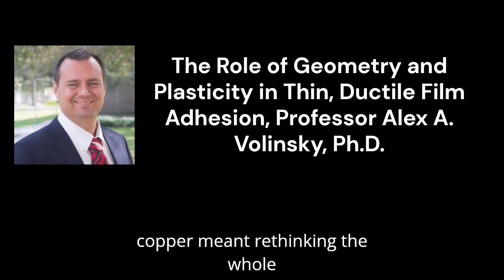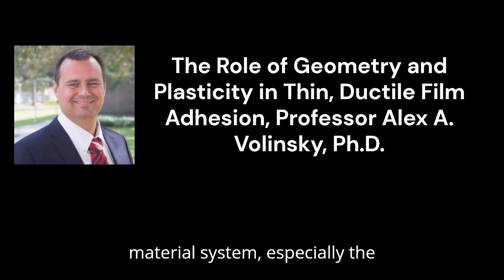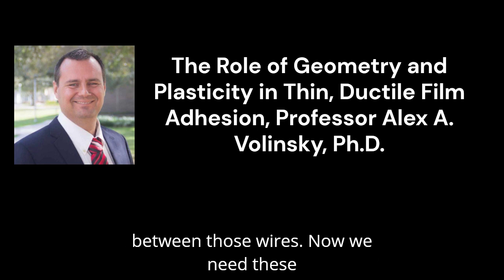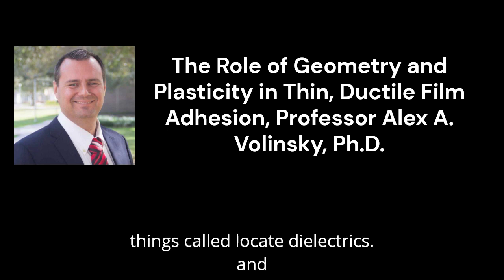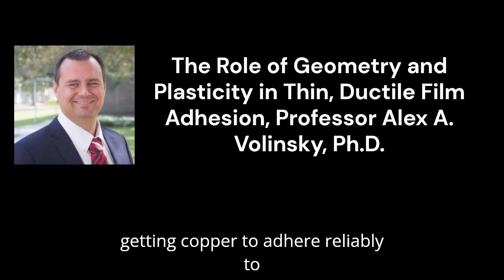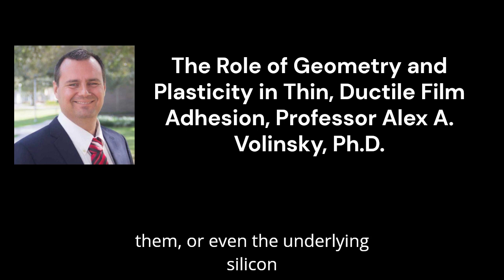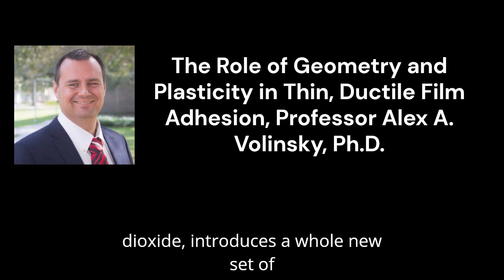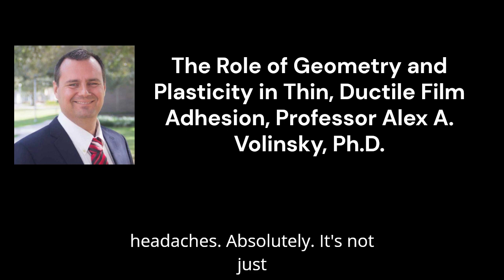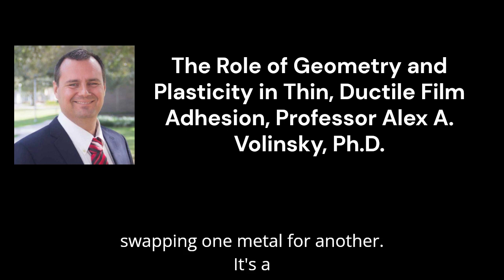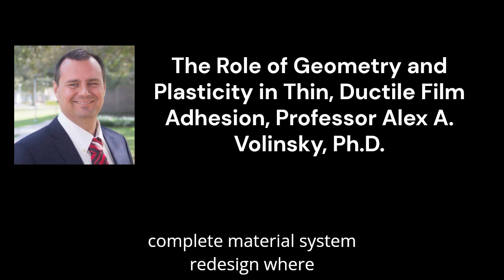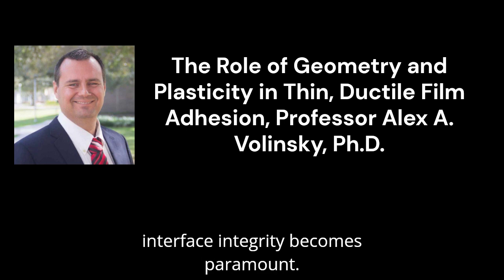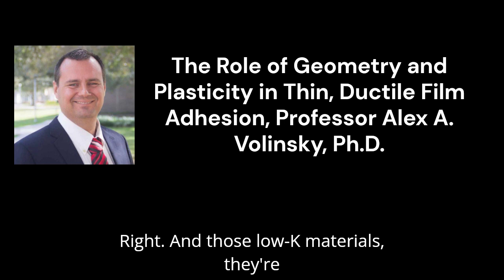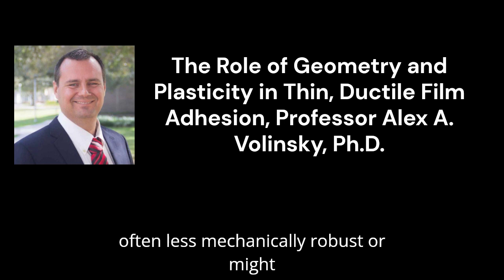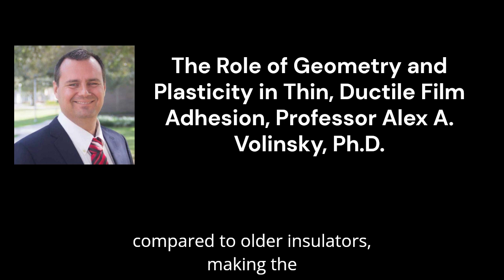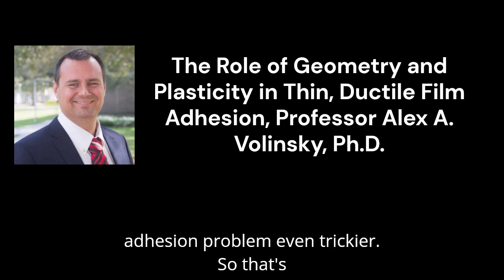But bringing in copper meant rethinking the whole material system, especially the insulating layers, the dielectrics between those wires. Now we need these things called low-K dielectrics. And getting copper to adhere reliably to them, or even the underlying silicon dioxide, introduces a whole new set of headaches. Absolutely. It's not just swapping one metal for another. It's a complete material system redesign where interface integrity becomes paramount. Right. And those low-K materials, they're often less mechanically robust or might have different surface chemistries compared to older insulators, making the adhesion problem even trickier.